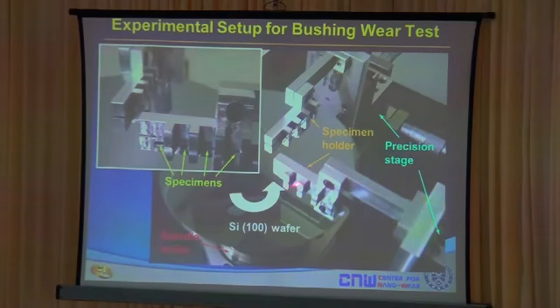What we do is a very simple experiment. We create these 3 bushings on the silicon specimen and reverse the specimen on top of a counter surface, which is also a silicon. So this is the counter surface, it's silicon, and the specimens are placed in these pockets here. There are 3, and these specimens are allowed to slide against this silicon wafer as the silicon wafer rotates slowly. Now we try to rotate it at a certain speed so that the top specimen will not bounce around.